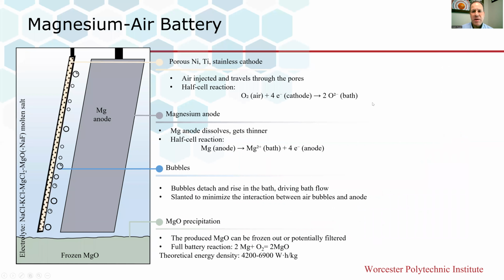So I'll turn next to a magnesium air battery. This is a battery intended for shipping, rail, and aviation. Looking at the cell level, we have a magnesium metal anode and a porous cathode made out of nickel, titanium, or stainless steel. We inject air through that porous material into a molten chloride salt electrolyte. At the cathode, we have the reaction of oxygen plus electrons making oxide ions in the bath. At the anode, the magnesium dissolves and gets thinner over time, producing magnesium ions in the bath.